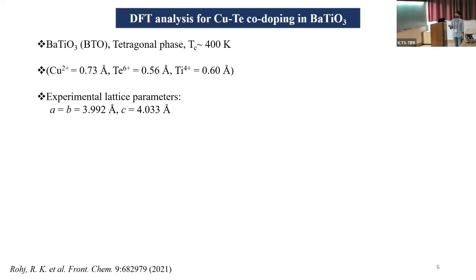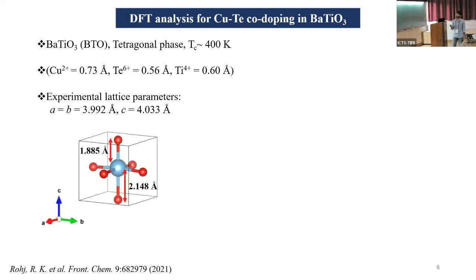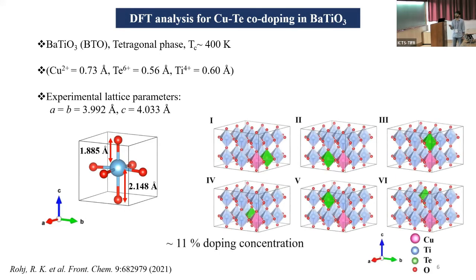We chose the experimental lattice parameters for the unit cell to be a equal to b equal to 3.992 angstrom and c equal to 4.033 angstrom. We considered the unit cell and optimized the internal coordinates. The titanium-oxygen bond lengths after optimization came out to be 1.885 angstrom and 2.148 angstrom, which matches with the literature. Using this optimized lattice unit cell for barium titanate, we created 6 symmetry-distinct supercells of size 3 cross 3 cross 2